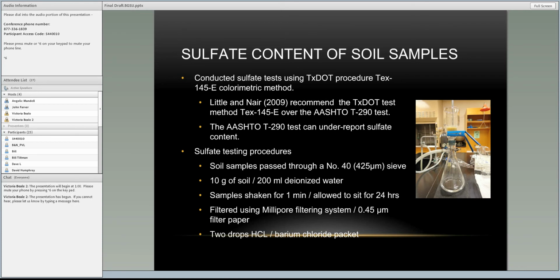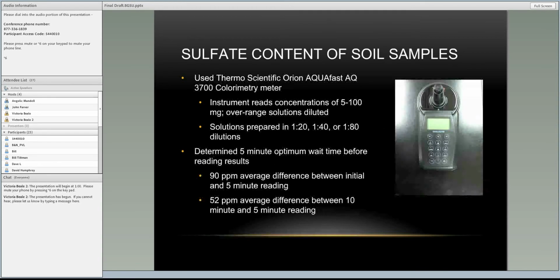Once we got the filtrate, to get a 1 to 20 dilution, we took 10 milliliters of the solution, added 2 drops of hydrochloric acid, mixed it up, and then added a barium chloride packet to it. And then we would put it into our colorimetry meter here off to the right. This unit only measures sulfate in the 5 to 100 milligram range, so a lot of times dilutions were needed. So we started with the 1 to 20 dilution. Sometimes we dilute it 1 to 40 or 1 to 80 to get a sulfate reading.